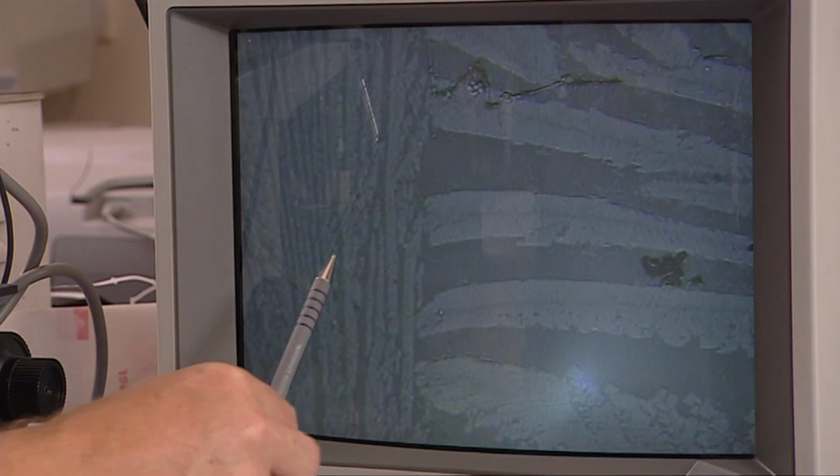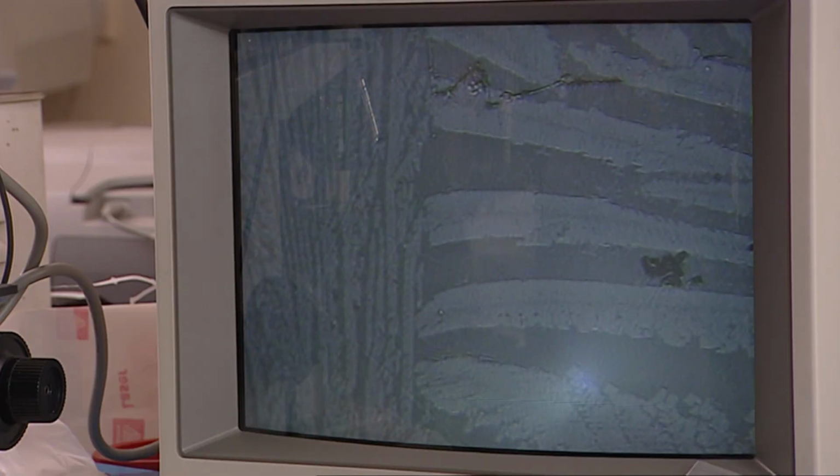But how about East Wall? Oh, no, it doesn't have the little Christmas tree structure. That's right, no dendritic stuff at all. It is there, but it's incredibly fine. What this means is that the process at East Wall was tremendously efficient. It's got really strong reducing conditions, which means that they are being most efficient. They're reducing every available piece of iron oxide to metal.